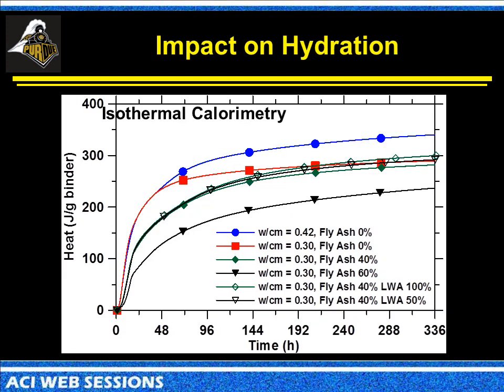A way that you can look at that is from some of these heat curves. These are heat generation curves from isothermal calorimetry. What we can see is obviously if we go from a 0.42 water to cement ratio to a 0.3 water to cement ratio, we're going to have differences. This difference between the 0.42 and the 0.3 water to cement ratio comes up because we're essentially starving the system for water. So you can't have hydration taking place, or you have a slower hydration taking place in these systems because there's not enough water in there to hydrate all the cement.